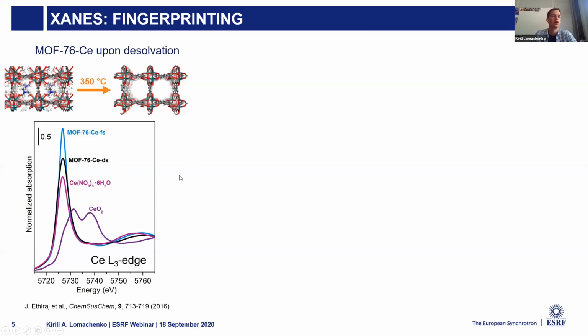When we do it, we see at once that the oxidation state of cerium in our MOF is cerium-3, because it looks very similar to the reference spectrum of cerium-3 and not at all like the spectrum of cerium-4. So like this, X-ray absorption spectroscopy can answer this question.